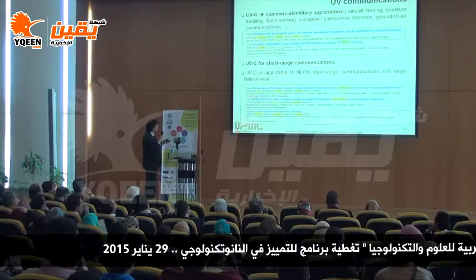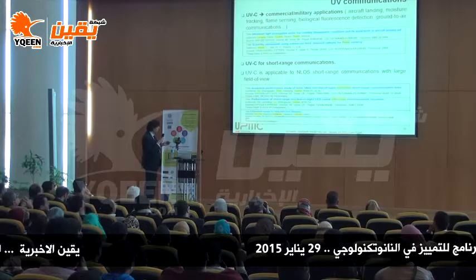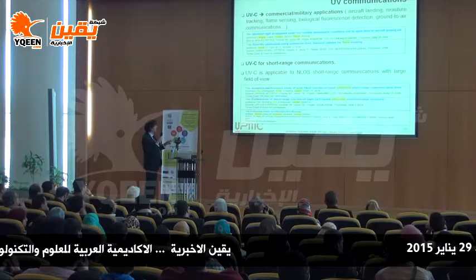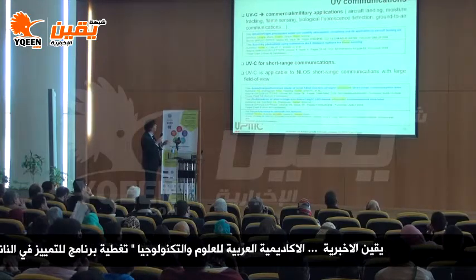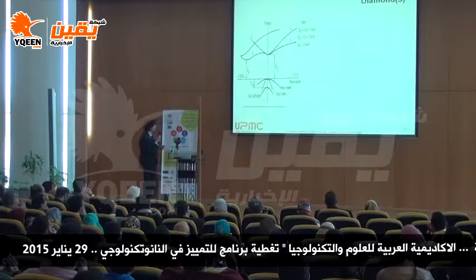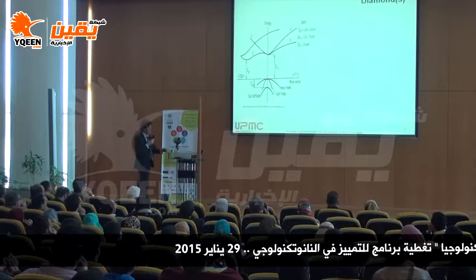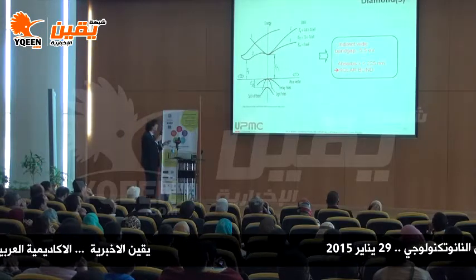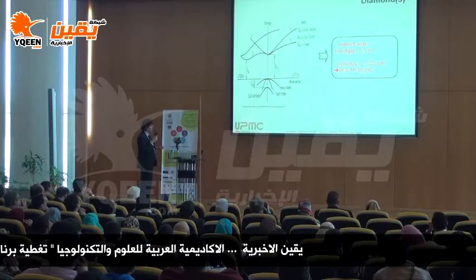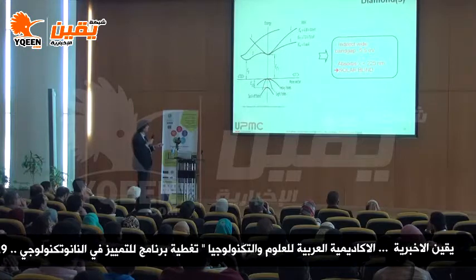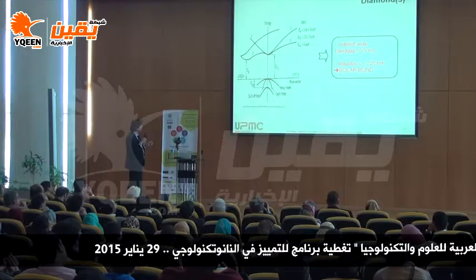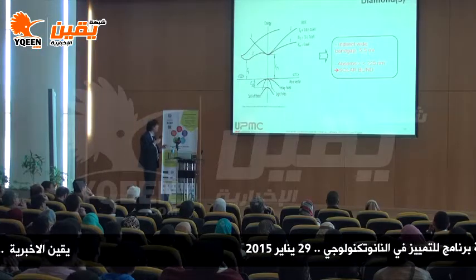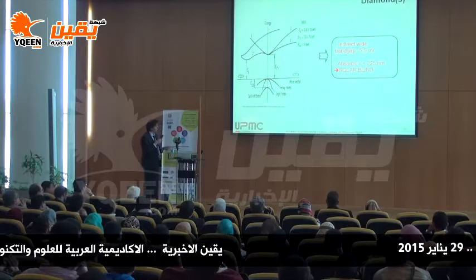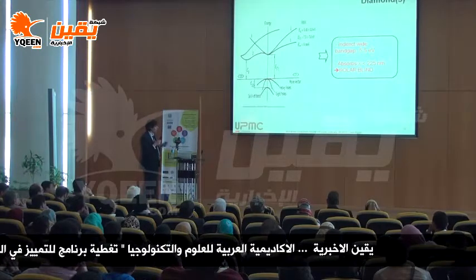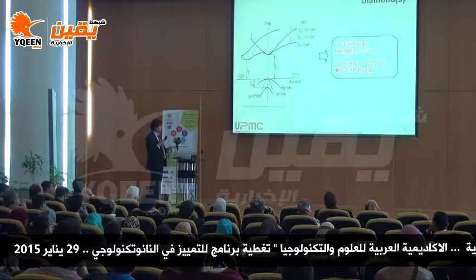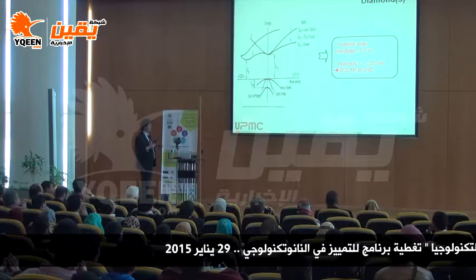Also with the UVC, there is a lot of work on non-line of sight application. That's mainly for when you have no visibility for aircraft landing and so on. So diamond, I put an s to diamond because actually we consider that there are different diamonds. The most common one has a gap of 5.5 eV. Indirect gap, so the top of the valence band is not aligned with the bottom of the conduction band, so we talk about indirect band gap. And the absorption, because of this large wide band gap, is below 225 nanometers, which makes such devices solar blind. So you would not be impacted by the solar spectrum.